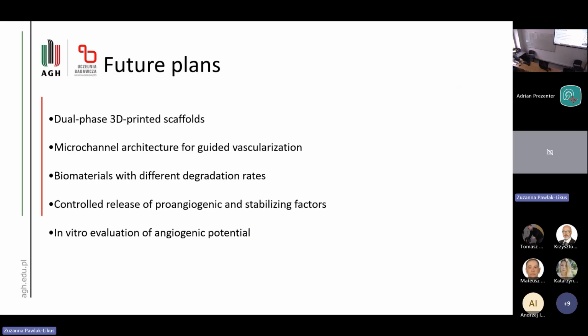The future plans for my PhD thesis are that we are planning to develop a dual-phase 3D printed scaffold with a microchannel architecture that is designed to support angiogenesis. So basically this concept is based on combining 2 biomaterials with different degradation rates. So the faster degrading phase is intended to create microchannel networks upon degradation, and those microchannels should serve as pathways for newly forming vessels. And while degrading, this material should release some pro-angiogenic molecules. And the second, slower degrading phase is designed to provide structural support and sustained release of bioactive components that may promote vessel stabilization and maturation.